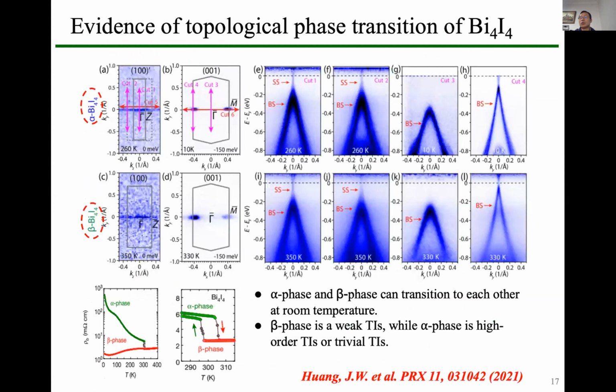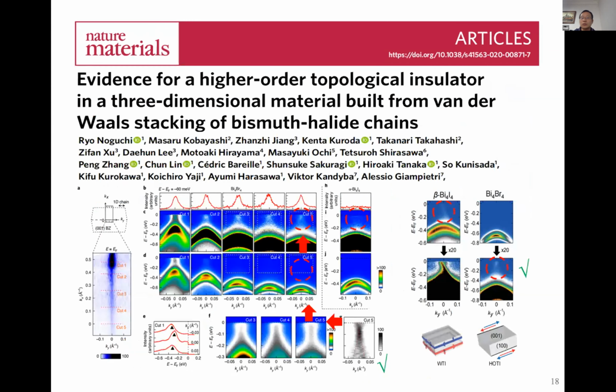To explain the contradiction between the two groups, each group observed a first-order structural transition between two distinct phases in bismuth iodide at room temperature. This structural transition results in a topological phase transition. By using ARPES, they identified the high temperature beta phase to be the first weak topological insulator, with two Dirac cones on the 100 surface, and no Dirac crossing on the 001 surface. So this is consistent with the calculations. But for the low temperature alpha phase, the topological surface states on the 100 surface open a gap. So this is inconsistent with the calculation.